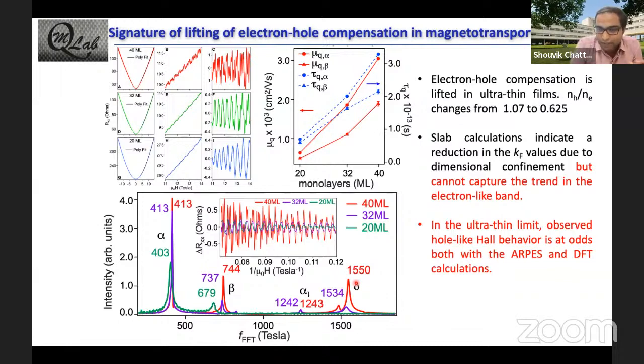So one, as I just mentioned before, our slab calculations really cannot capture the correct trend, though we saw that in the bulk limit, DFT does a very good job of representing the actual electronic structure that we measure. That is one. And the second, if you remember a couple of slides back, I showed you that in the ultra-thin limit, you had the Hall behavior changing from electron dominated to hole dominated, which is clearly not what we are seeing from our ARPES and the quantum oscillation measurements. So can we reconcile what we are seeing in our measurements?